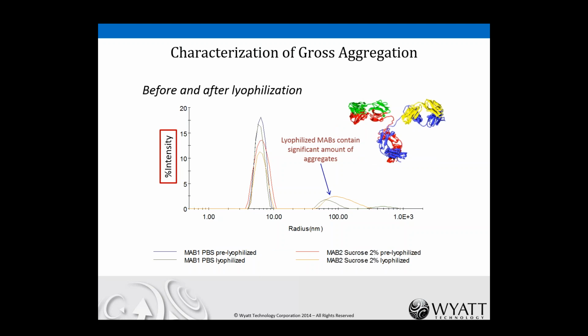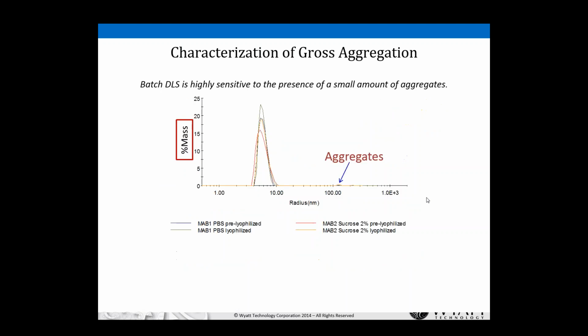So light scattering intensity is proportional to molecular weight, and that means that if you go to something with a very large molecular weight, you're sensitive to the presence of a very small amount of it. When you get up to something on the order of 100 nanometers, you're looking at molecular weights which may be hundreds or thousands of monomers, and when you're up in the hundreds of nanometers, you're talking about many, many millions, if not more. So these are very large aggregates, and we're sensitive here to the presence of a very small amount of them. And that's what I show over here. This tiny amount that you see here is probably on the order of just a few particles in that well.